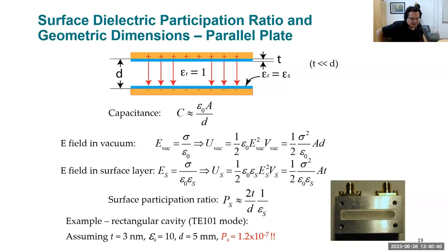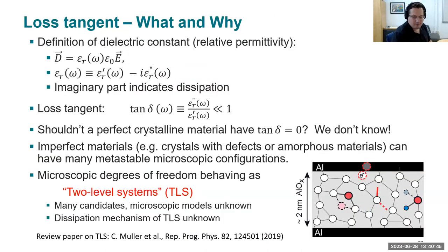Why did you draw the stuff in between the layers as AlOx instead of Al2O3? These are the elemental composition of aluminum oxide. I think it may be close to aluminum 2, oxygen 3, but it actually is amorphous, so the composition can vary. It has a different bonding configuration. So generally people write just an x, representing that the numbers may vary.